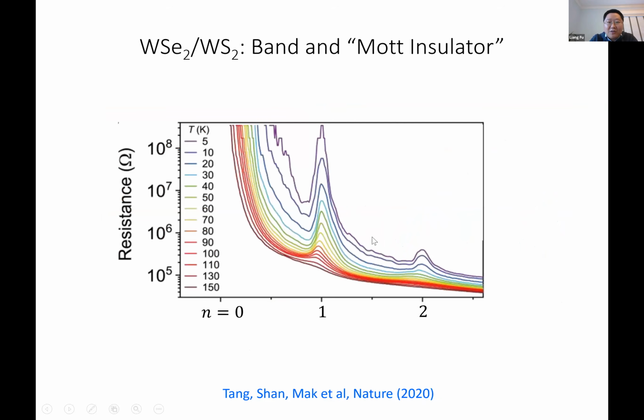Okay. So very recently, there are two, I think, pretty remarkable experiments. The first one is from the Cornell group, and they look at this tungsten diselenide, tungsten disulfide, and as you dope the holes into the Moiré bands, you see that when the Moiré band is completely filled by 2 holes per unit cell, an insulating state appears. This is what we expect for a band insulator with a complete filling of bands. But at half of that filling, with 1 hole per Moiré unit cell, another insulating state appears. That was described in this work as a Mott insulator. Certainly, it's a correlated insulating state which appears at low temperature.